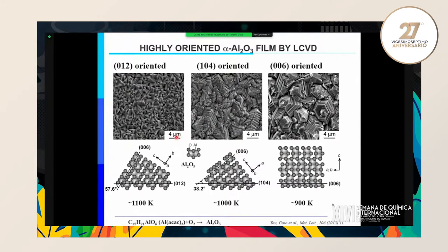and 012 oriented alumina. So generally, in a hexagonal structure like alpha alumina at a low temperature, the 001, 006 basal plane is likely to become parallel to the substrate, and at higher temperature the hexagons are slightly slanted. Without using a single crystalline substrate, even on polycrystalline or tungsten carbide cutting tools, we can prepare a very oriented film in at least one direction, the growth direction. For a cubic structure, for example beta silicon carbide, at low temperature the 001 plane is parallel to the substrate, and with increasing temperature it slants to 110 or 111 orientations.